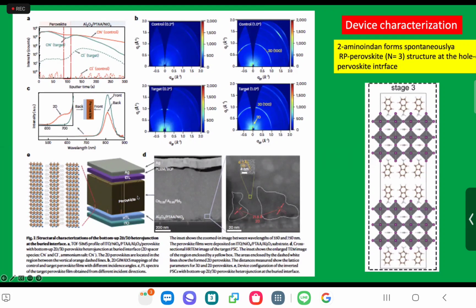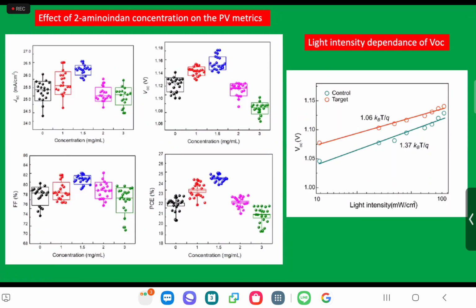Nature just helps us, with spontaneous formation of this. It's 2-aminoindane that does that for you. And here it's a Ruddlesden-Popper structure. It's mainly n=3. All this has been sorted out. And if you take the cryogenic focused ion beam analysis, you can actually see a 2D layer on the bottom. So there's evidence. It's not fantasy or speculation. Several independent experiments show that this happens. So I hope I have convinced you.